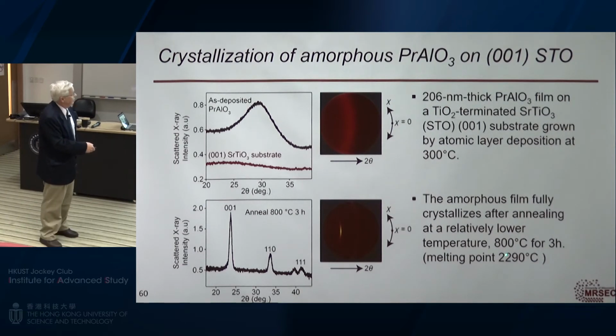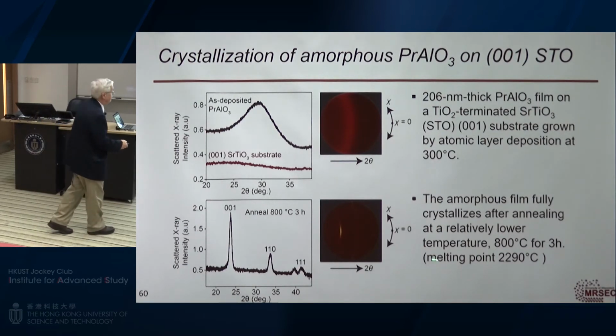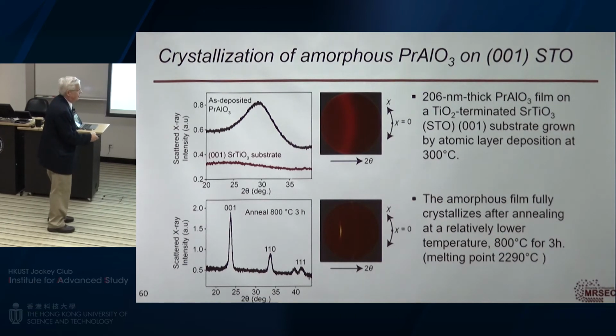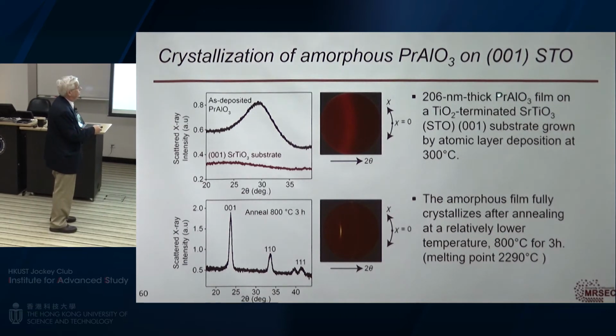Now what's significant is that the melting point for praseodymium aluminate is almost 2300 degrees centigrade. And we usually say you have to be at two-thirds of the melting point to get a lot of diffusion in the solid state. So we are very, very low. And hence, there's not a lot of solid state diffusion. All this allows us to do is to reorient maybe one or two atomic sites near that interface.